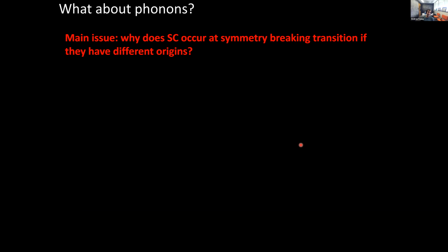Your Fermi temperature is actually very small, but that turns out to be okay. The theory of the so-called anti-adiabatic limit of superconductivity was worked out, I think, mostly by Gorkov. And you will get BCS superconductivity also in this limit. Rather than omega Debye times some exponential factor, it's T Fermi times some exponential factor. That seems very reasonable here.